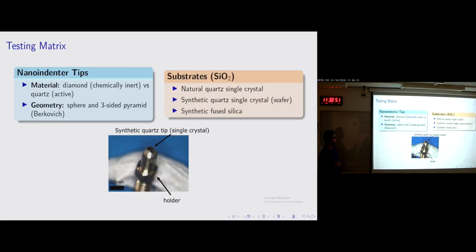So let's look at the testing matrix here, starting with the nanoindenter tips. We use two types of materials: chemically inert diamonds and a chemically active quartz tip. And this is an example of a quartz tip. It's hard to see because I just took a picture with my phone. It's not really good. I bought these synthetic quartz single crystal wafers. I cut them down to really, really small rods. And I shipped them to a company in Switzerland, and they were fantastic, and they were able to make these quartz tips. They made them for us with two geometries, a sphere and a three-sided pyramid. That's Berkovich. So this is an example, you can't really see the tip. It's a quartz Berkovich tip.